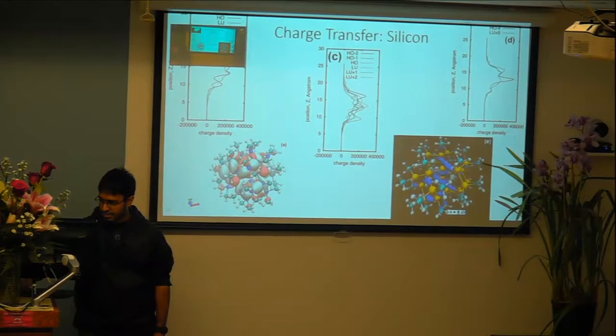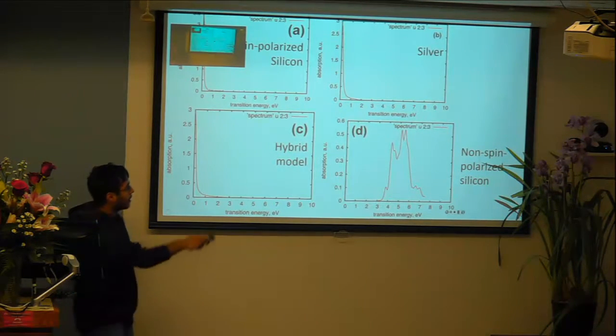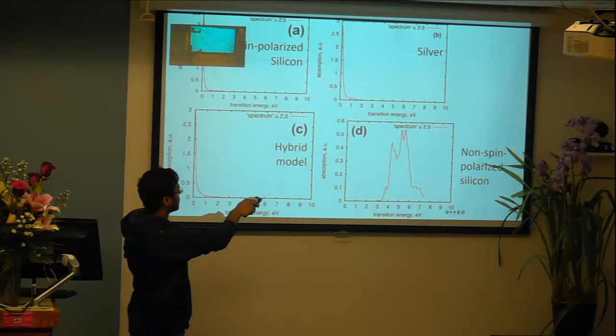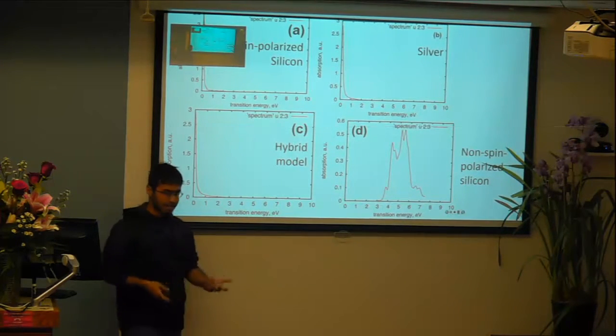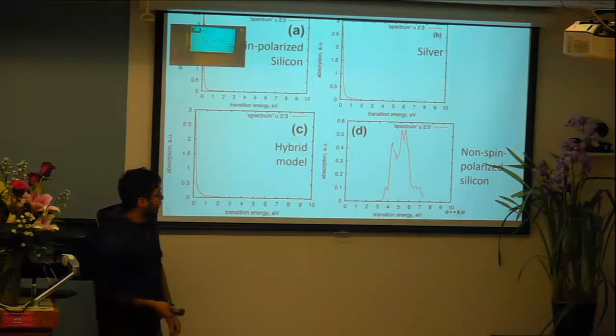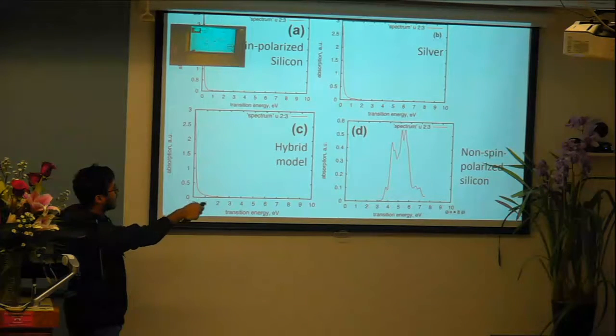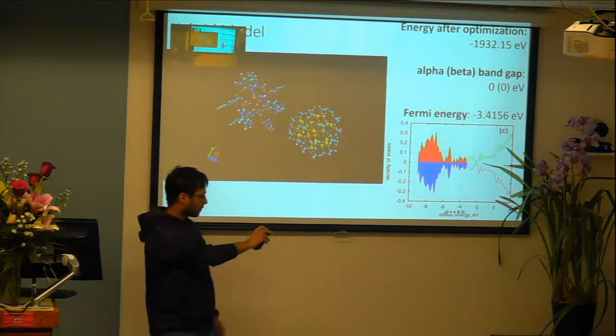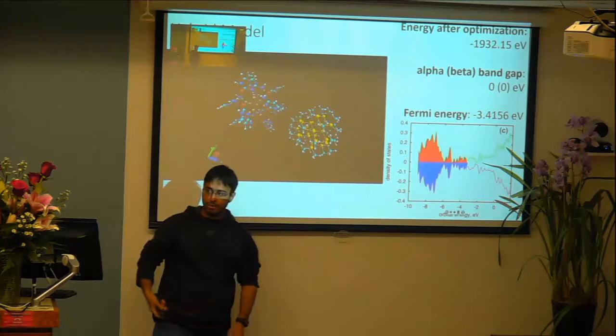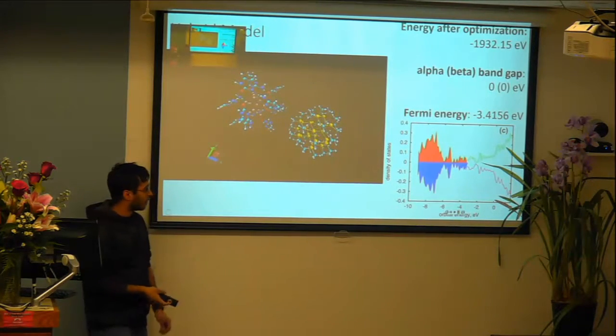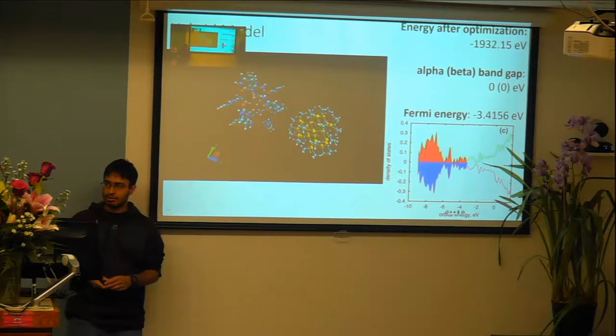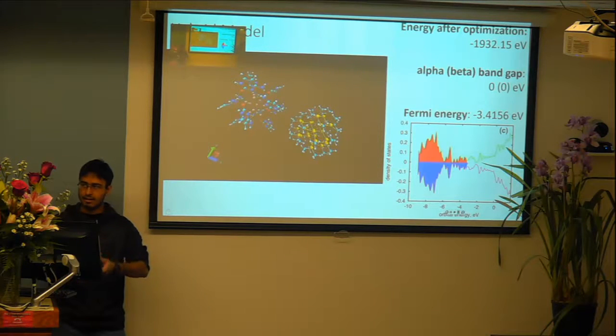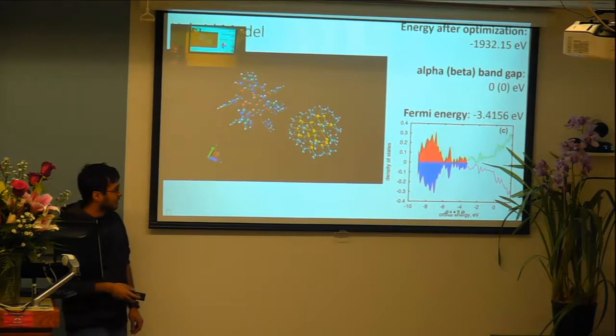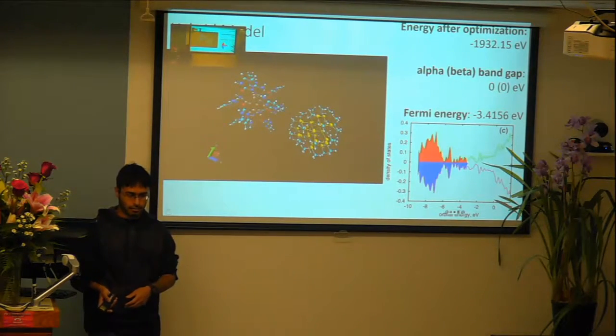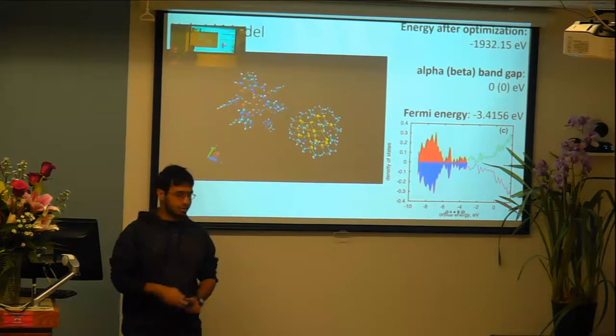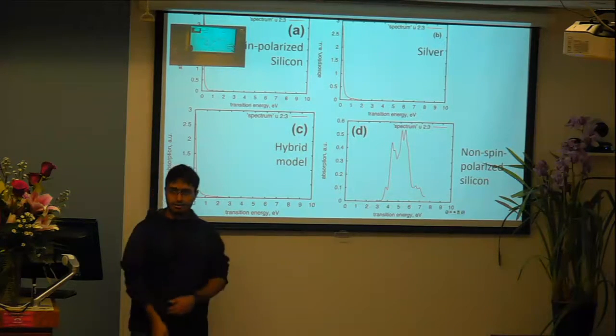Yeah, so I'll go back to the plots, right here. So the question was what the significance is of this absorption spectra having a peak at 0, how it could be removed, and if it's real or not. So the peaks near 0 right here in the spectra were actually a consequence of having the HOMO and LUMO states be very close to each other. So the band gap was essentially 0, which means that electrons did not need to have much energy in order to go from one state to the next state when you're trying to excite the electrons. And in order to actually combat this, one would need to oxidize the model more, or in other words, remove more electrons from the model in order to have these peaks appear at higher transition energies.